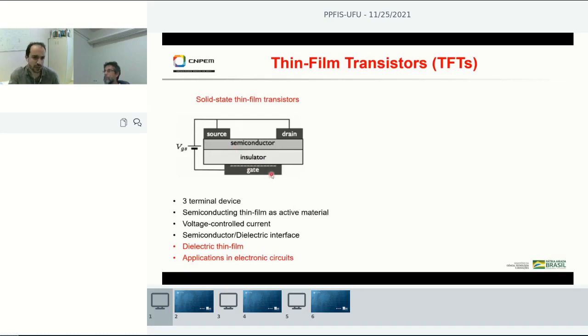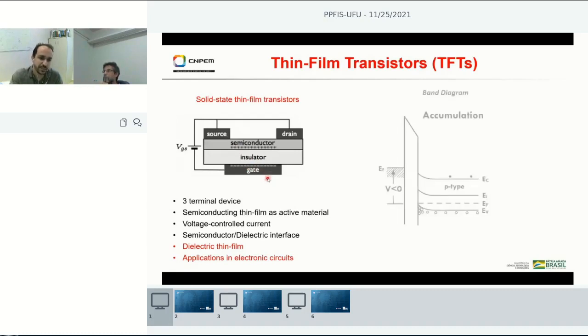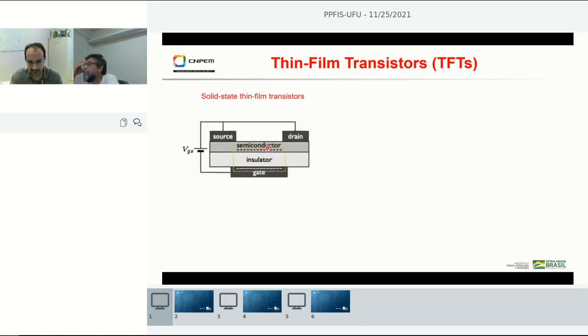So, for example, by applying a negative gate potential, you induce accumulation of charge carriers, for example, p-type carriers in the channel, then you can control the current that flows in the semiconductor. This is the typical band diagram for a p-type semiconductor in a metal insulator semiconductor structure. So by applying, for example, negative gate voltage, you induce holes in this interface.